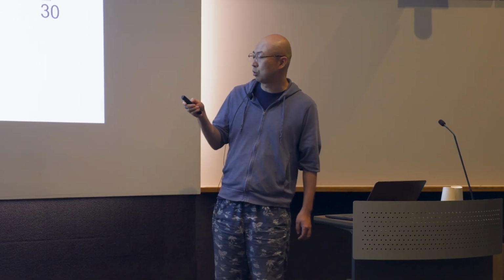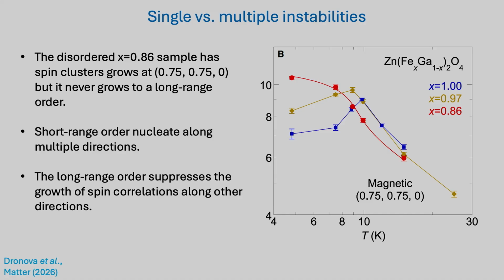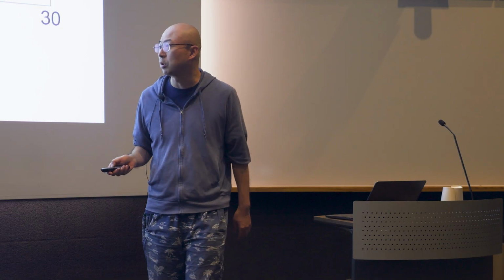It's always small. It's basically only a 30% increase compared with the 15 Kelvin. At the off spectral position, for the clean sample, you actually have a reduction of the correlation length. So basically that confirms the redistribution of the spin spectral weight to other positions. However, for the spin glass sample, the correlation length keeps on increasing, which means that the short range order in this system grows a little bit. So both at your magnetic position and at your off magnetic position, your short range order grows a little bit, in both cases.